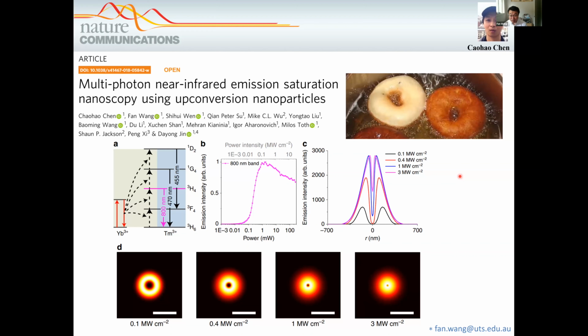We just need to generate one donut beam. And using one donut beam combined with this saturation, it's really easy to achieve super resolution. So what we did is we shine a donut beam on the sample. So this is a single nanoparticle. And once we increase the power, because everything will be saturated, you will see the middle hole come to smaller and smaller. And because, if you still remember what we discussed previously about cross-relaxation, the 800 energy level got the population inversion. So it's really easy to be saturated. And we just need to use a small power like 50 milliwatt or even 10 milliwatt. We can saturate the material and we can achieve a really small hole in the middle.